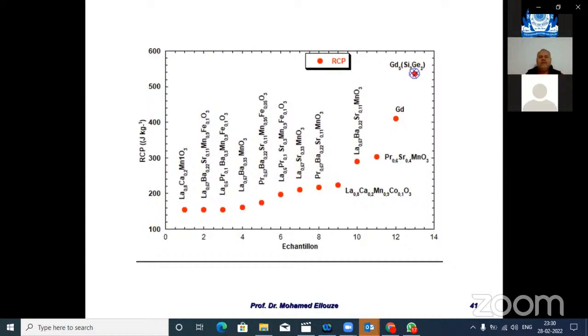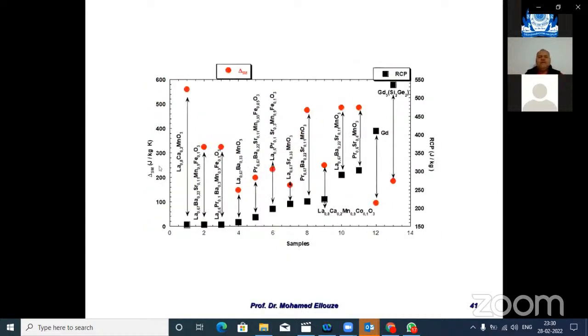Here also is the variation of RCP as well as the variation of magnetic entropy. We can see that for this kind of sample we have lower magnetic entropy but a good RCP. But for the other sample, it's the opposite: we have lower RCP but a good value of magnetic entropy variation.